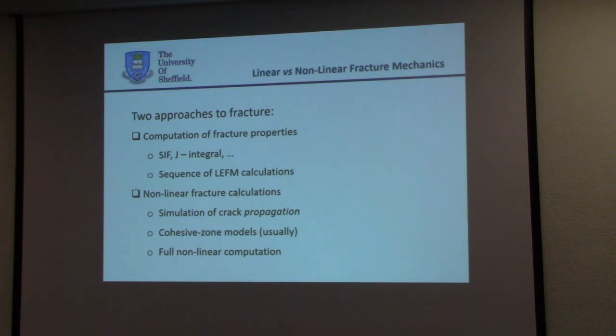Now, the following thing. Essentially, you have two approaches to fracture in computations. One is the computation of fracture properties. You compute stress intensity factors, J integrals. Based on those data, you decide whether further fracture occurs or not.